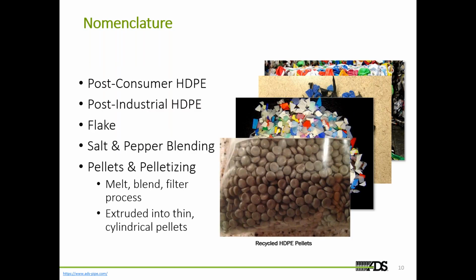And then finally, and Michael had a nice photo of this in his presentation, I think this is maybe the same photo, pellets and pelletizing. After ADS processes that post-industrial or post-consumer recycled material, we have it in its flake form. And before we make it into pipe, for the most part, we then make that flake into pellets. There are two large reasons why we make that flake into pellets before we make the pipe. One is increased homogenization of that material. So when we take that flake, whether it's from post-industrial or post-consumer, we homogenize it by making it into pellets.